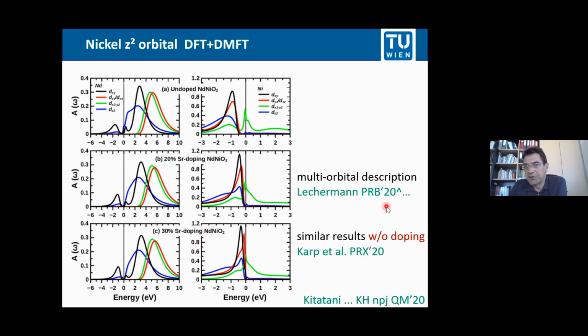And there are also some other studies, so there is still some controversy in the literature. And let me just mention one, namely Frank Lechermann, because he did his PhD at the Max-Planck Institute in Stuttgart. So he says that the Z-squared orbital is also relevant and more filled than in these results. But he takes very unrealistic large U interactions and doesn't take the nickel D interaction into account. So that means that up to the superconducting doping regime, also the Z-squared orbital can still be disregarded. If we do the proper calculation, we include it, but we see it's not relevant. So how about the 4F?